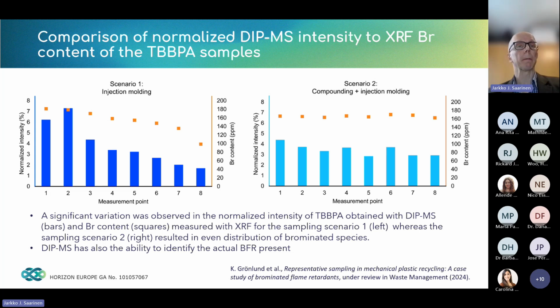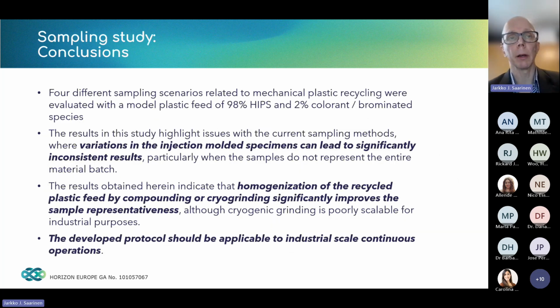So then, for the sampling study, some conclusions that can be derived from these analytics is that indeed we used 4 different sampling scenarios, which were related to the mechanical plastic recycling. Were evaluated with model plastic feed of 98% of the non-contaminated high-impact polystyrene, and then 2% either colored or then brominated species.